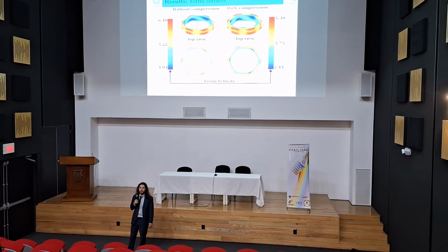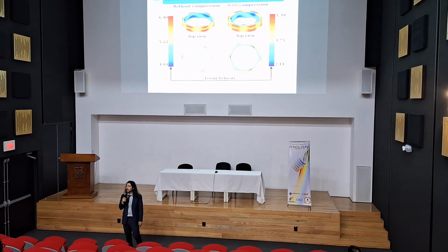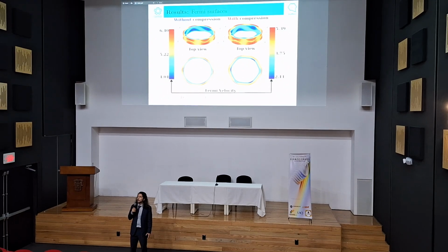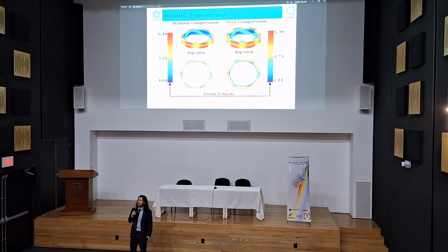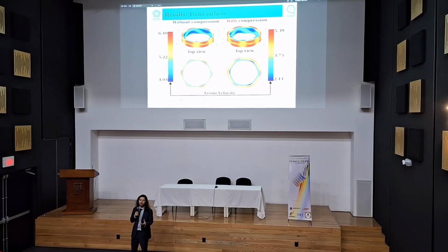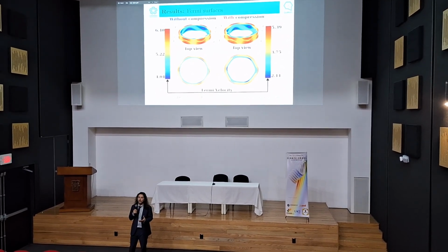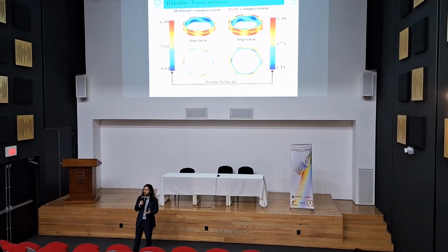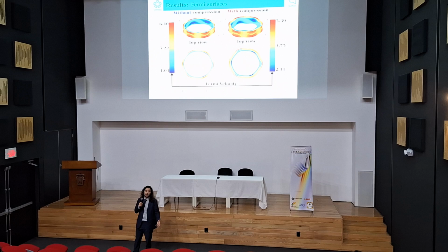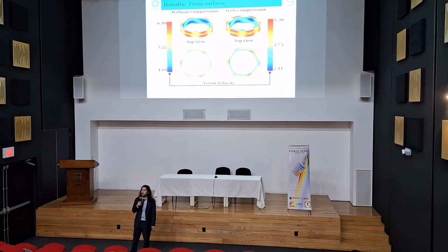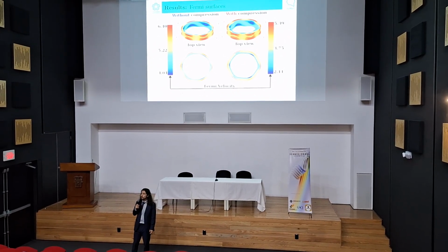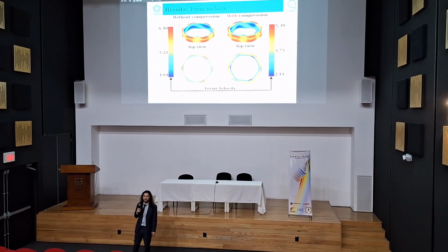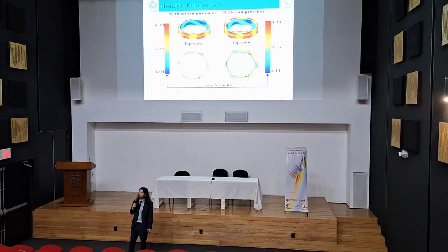Also, the Fermi surface showed the distribution of the Fermi velocity on the surface. And as you can see, with the compression, the Fermi surface tends to deform, which means that the electrical properties of the material must change. And also, the Fermi velocity decreases according to the color bars in the scheme.